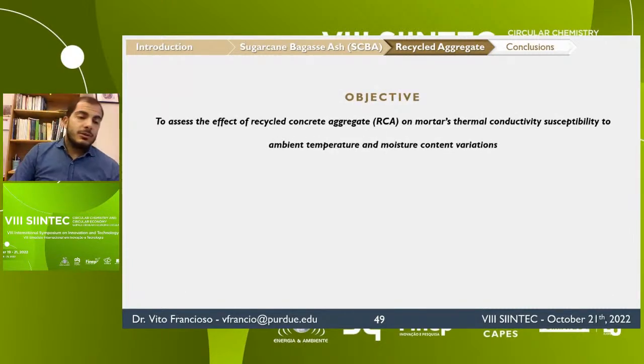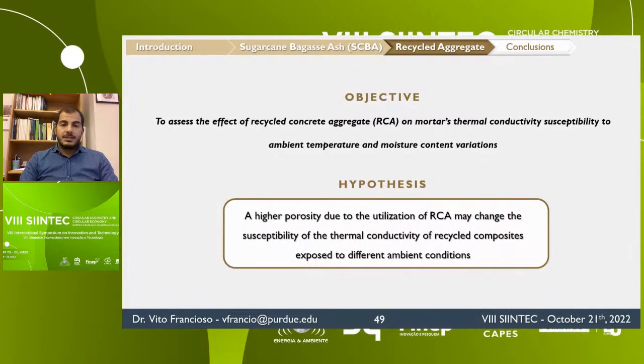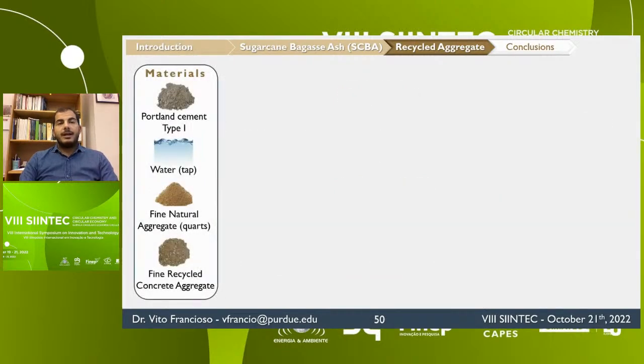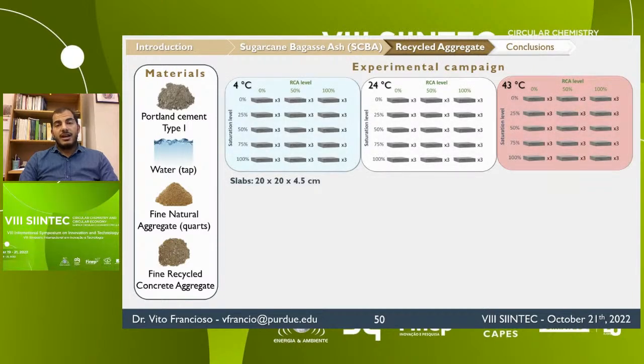So the objective for this study was to assess the effect of recycled concrete aggregate on mortar's thermal conductivity susceptibility to ambient temperature and moisture content variation. The hypothesis is that the higher porosity due to the utilization of recycled concrete aggregate may change the susceptibility of thermal conductivity of the recycled composite exposed to different ambient temperature. Here I designed 4 mixtures with 0, 25, 50, and 100% of recycled concrete aggregate. However, only 3 of them were selected for assessing the thermal conductivity, while the other one, the 25% replacement, was used to validate the model that I will present later.